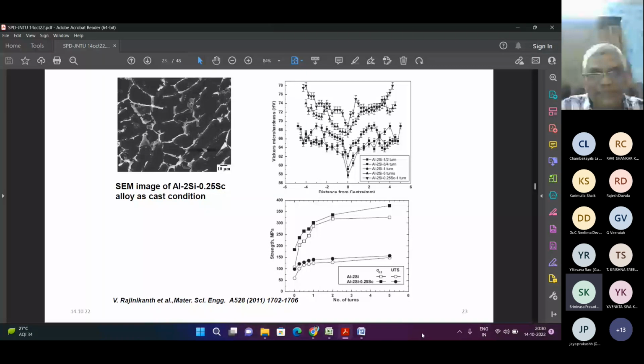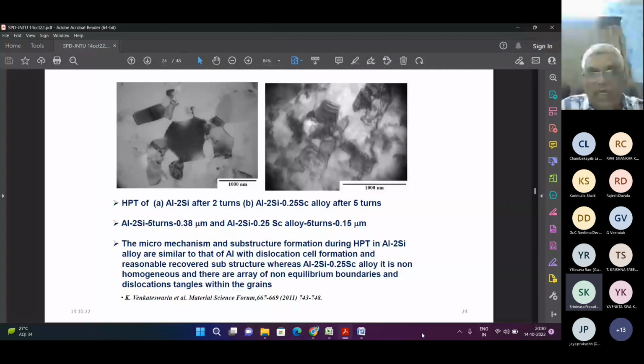So this is not the aluminum 2 silicon alloy alone. We have done the aluminum 2 silicon 0.25% scandium, and you can see beautifully how the grain size is reduced to less than a micron, to nano size. You can see the beautiful grain sizes which are very, very small.